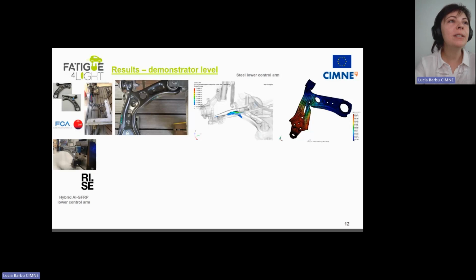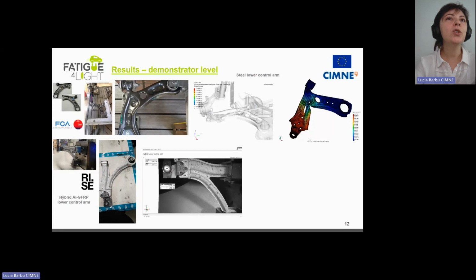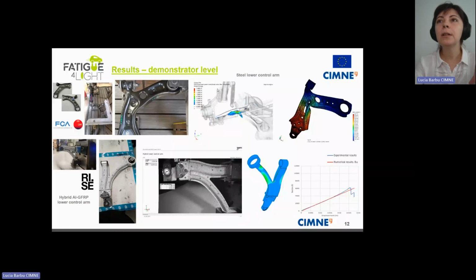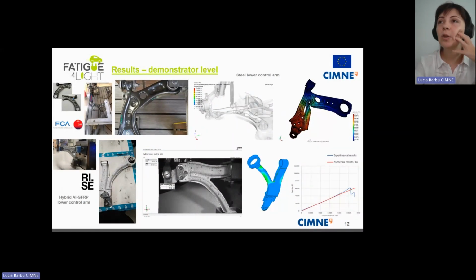Okay, now about the hybrid aluminum GFRP lower control arm. This was a different version of this geometry. It was manufactured and tested at RISE, and you can see here some images of the test being performed, and also an image of the failed specimen, again in the monotonic regime. From TeamNet side, we were also involved, and we are continuously doing the modeling for this geometry. And you can see a preliminary approximation that we obtained between the numerical result and the experimental result, at least for the elastic part at this point.